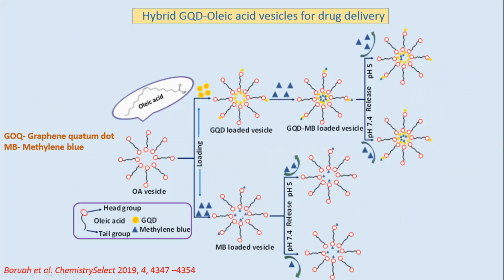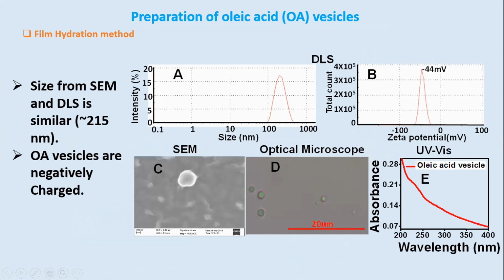And I found from the comparison that the composite system can load more drug, as well as release more drug at pH 5 compared to only pure vesicles. So for that, I prepared oleic acid vesicles. You can see this is the circular, or spherical, structure. From DLS also you can get similar structures, and the size of the particles was around 215 nanometers. Its zeta potential was -44 mV.